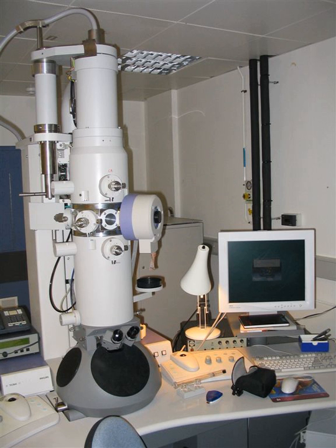Ion beam milling thins samples until they are transparent to electrons by firing ions, typically argon, at the surface from an angle and sputtering material from the surface. A subclass of this is focused ion beam milling, where gallium ions are used to produce an electron-transparent membrane in a specific region of the sample, for example through a device within a microprocessor. Ion beam milling may also be used for cross-section polishing prior to SEM analysis of materials that are difficult to prepare using mechanical polishing.